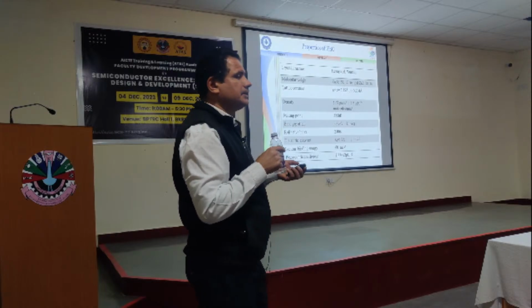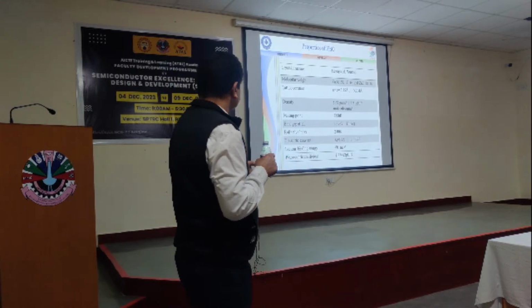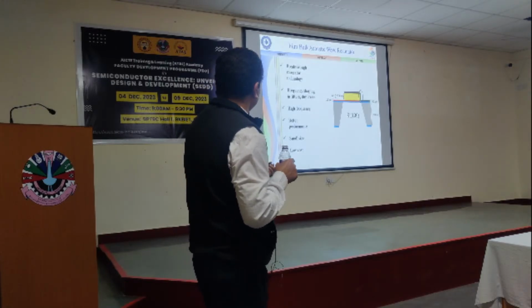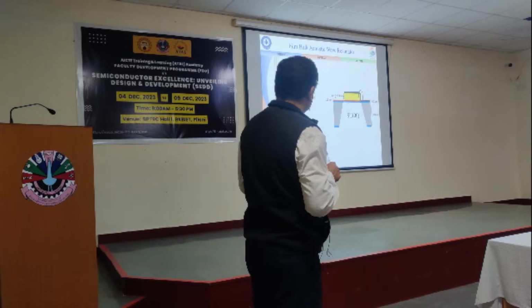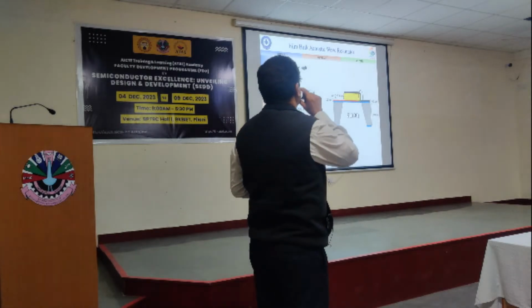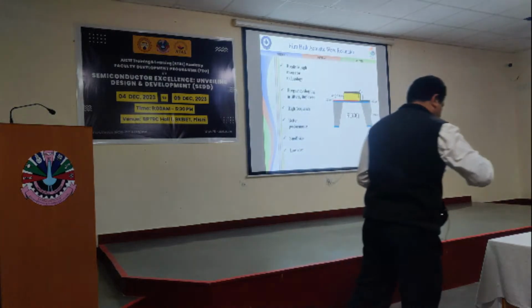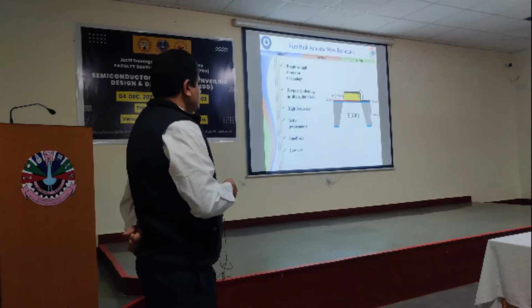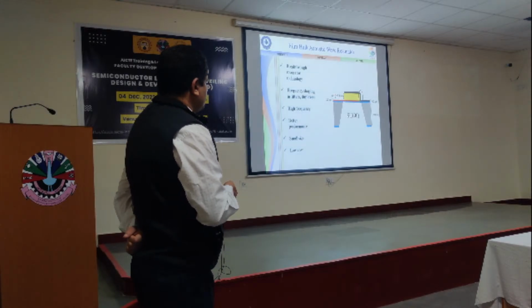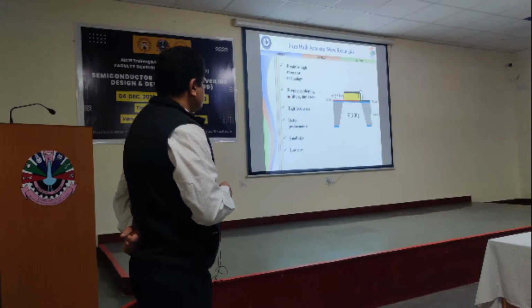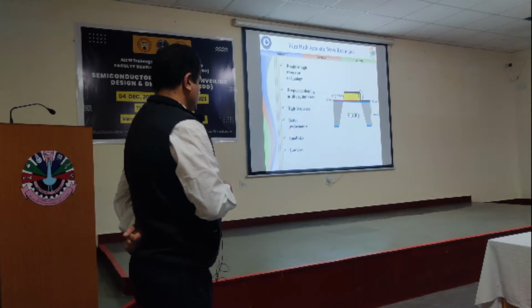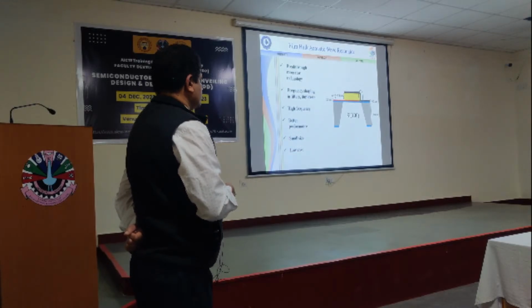In fact, this material we developed and utilized for our acoustic sensor applications. This was one of the devices we developed on silicon wafers. You see here, we deposited oxide, then the bottom electrode, then the piezoelectric layer, then the top electrode. This makes a resonator. We'll understand how it works as a resonator, but it is a very high quality factor resonator based on piezoelectric material. D is equal to lambda by 2. It is used in filters and reflectors operating at very high frequency, up to 10 gigahertz, providing better performance, small size and low cost.